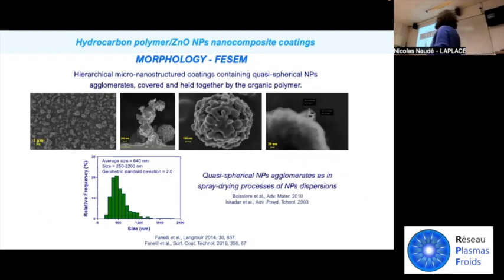So, as you can see here, these coatings are hierarchical micro-nanostructured coatings containing quasi-spherical nanoparticle agglomerates covered and held together by the organic polymer. It seems clear from morphological investigation that the polymer has a twofold role: it holds together the nanoparticle agglomerates in the three-dimensional porous structure of the coating, and it also has a very important role in the adhesion of the coating to the substrate.